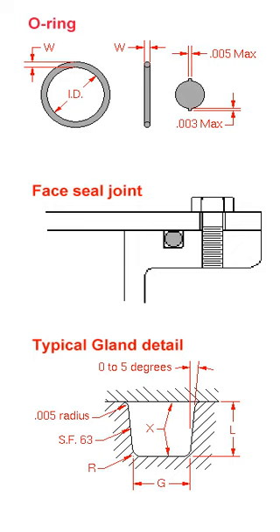The seal is designed to have a point contact between the O-ring and sealing faces. This allows a high local stress, able to contain high pressure, without exceeding the yield stress of the O-ring body. The flexible nature of O-ring materials accommodates imperfections in the mounting parts. Surface finish is also especially important in dynamic applications. A surface that is too rough will abrade the O-ring, and a surface that is too smooth will not allow adequate lubrication.